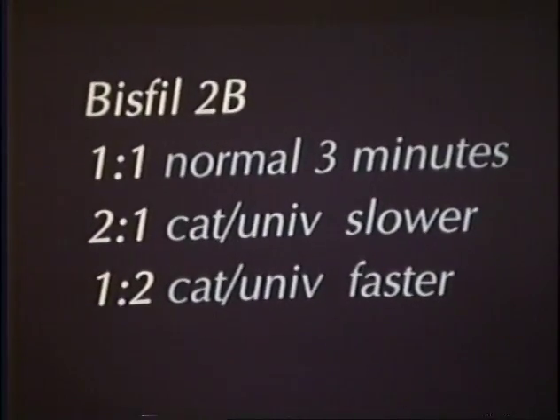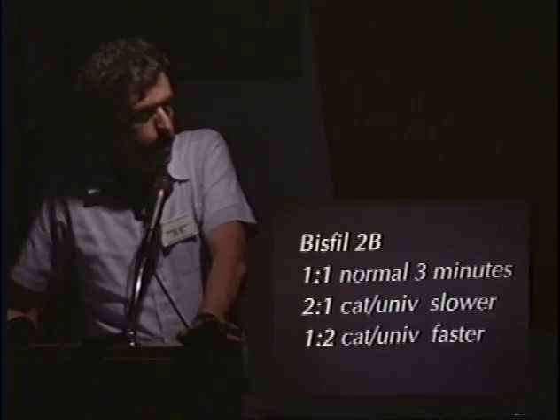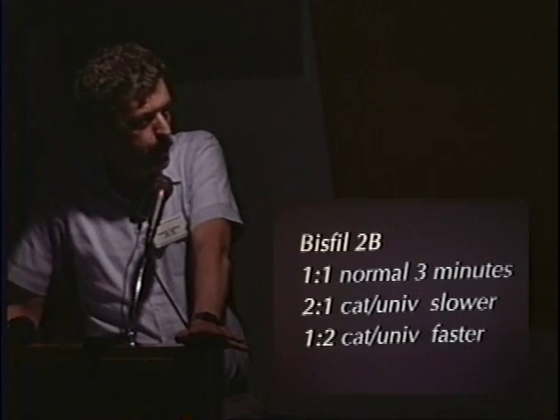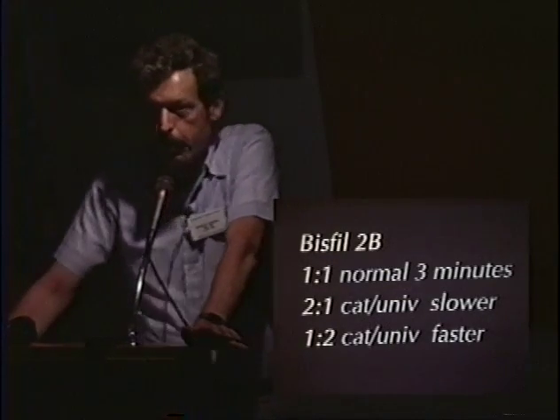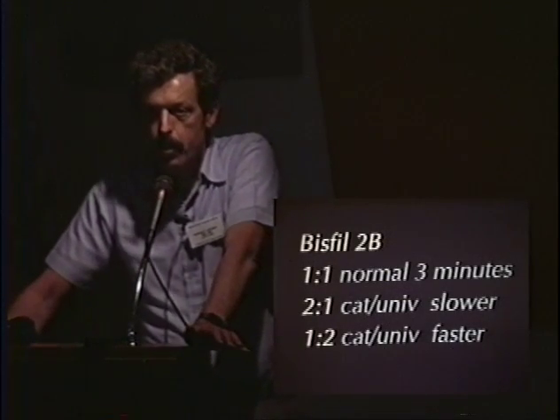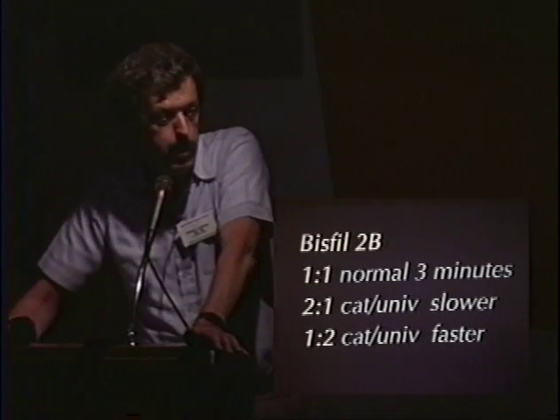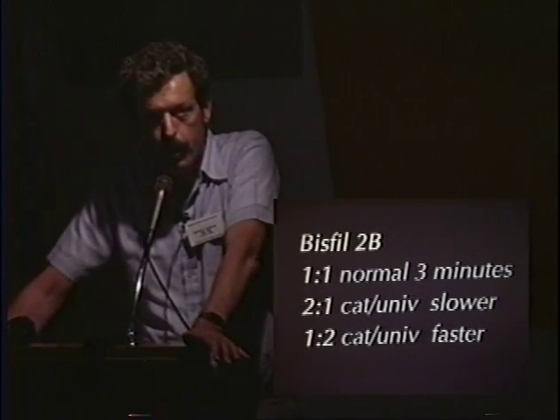Go ahead and light cure the Helio. That's fine. Appropriate time. Now here's the setting time. Bisfil 2B, as designed originally in San Leandro, California, which is room temperature 72, sets in 3 minutes from the start of the mix. Full polymerization, which means you have about 1 minute and 3/4 working time where you don't see any gelation yet.